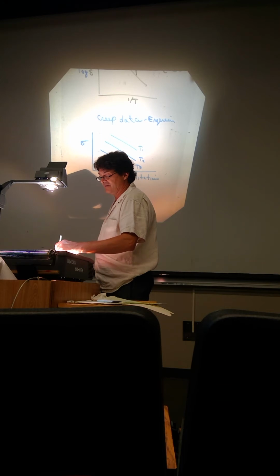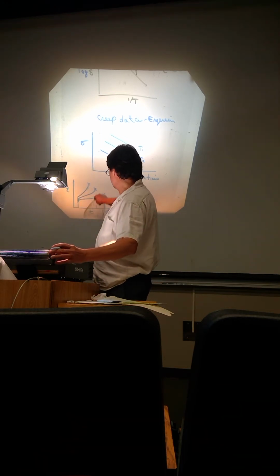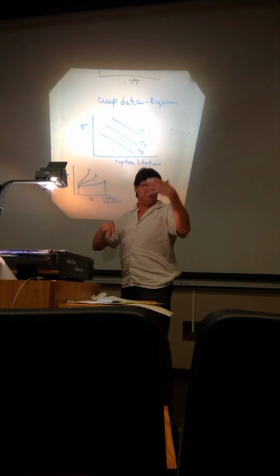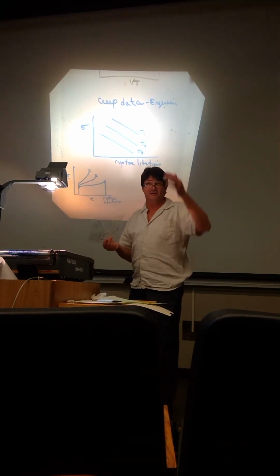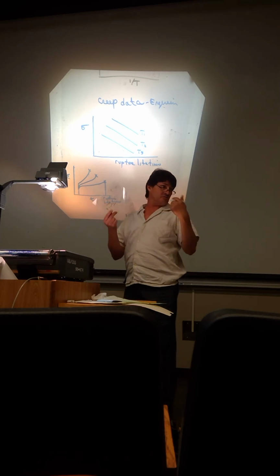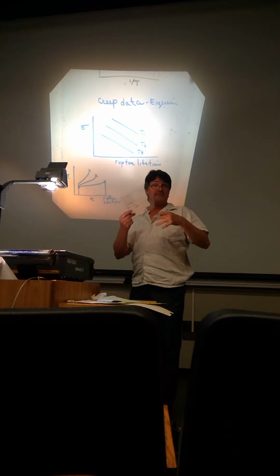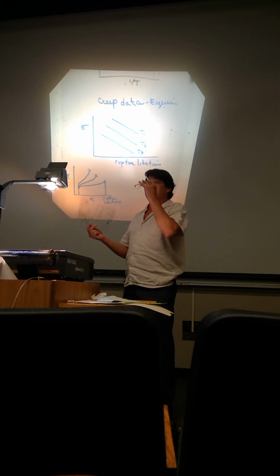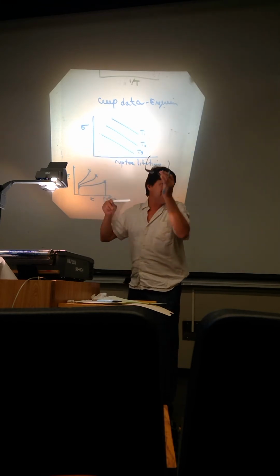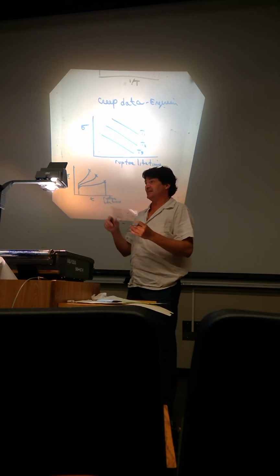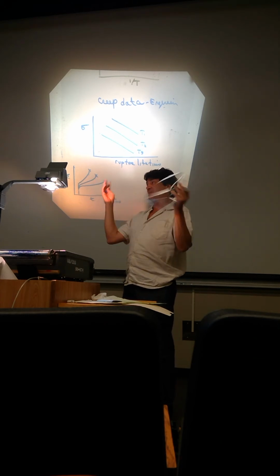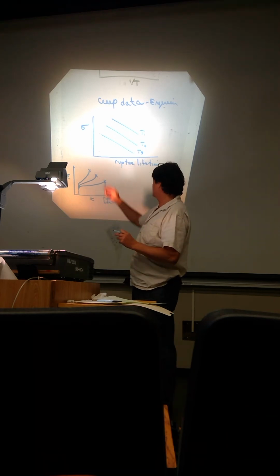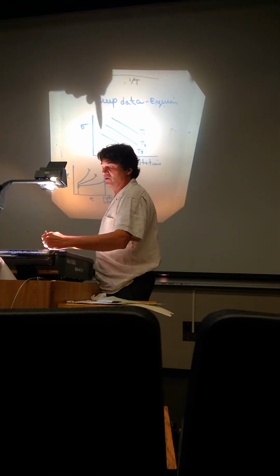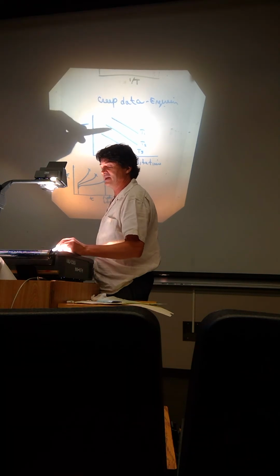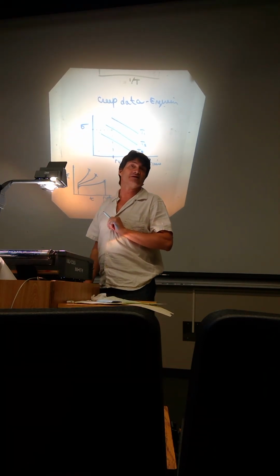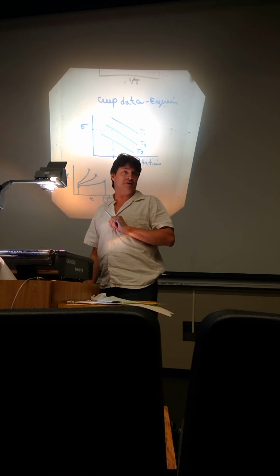rupture lifetime. So if you're designing something where the rupture is the critical failure mode, we looked at those 4 different types of failure. One of them was rupture limited. Like when your steam pipe bursts, that's an issue. If it just expands a little bit, that's not that big of an issue in the heat exchanger. The dimensions aren't critical; it's when the pipe actually breaks that is critical. You would use creep rupture lifetimes, so you would know that for a given stress, at a given temperature, you could predict your rupture lifetime. That's how you use creep rupture curves.